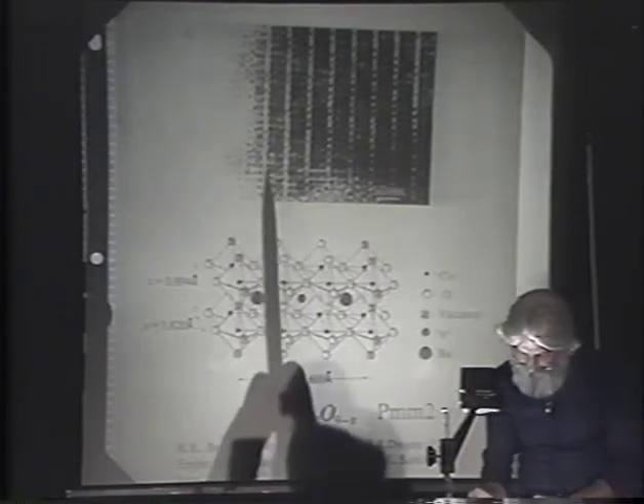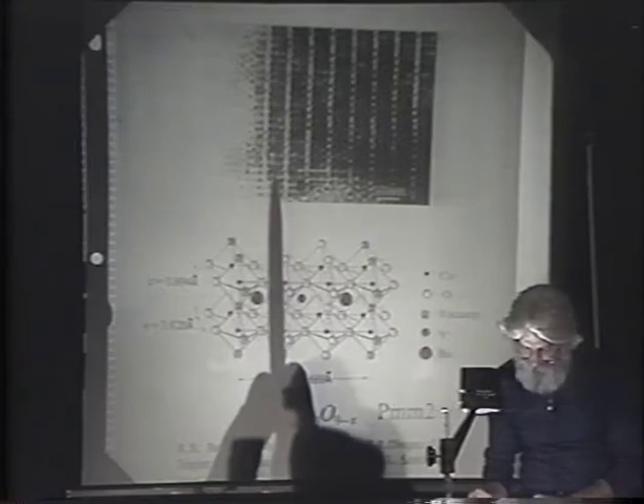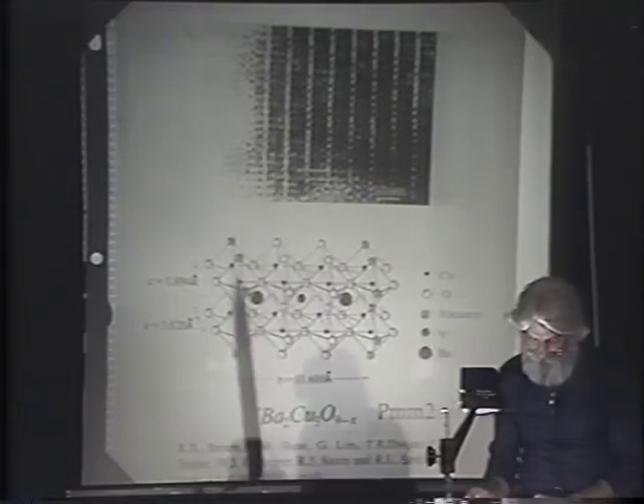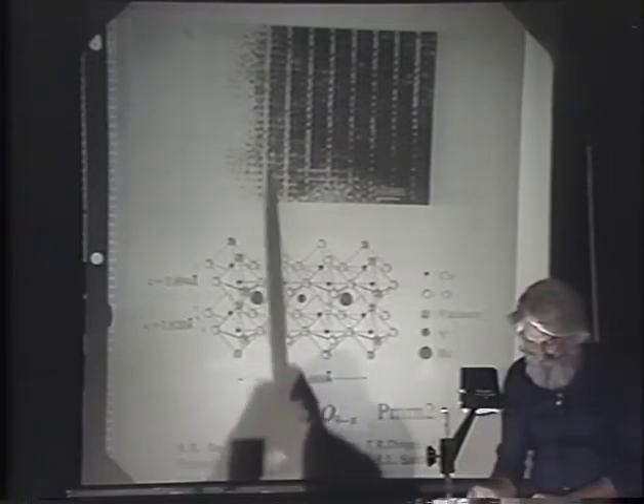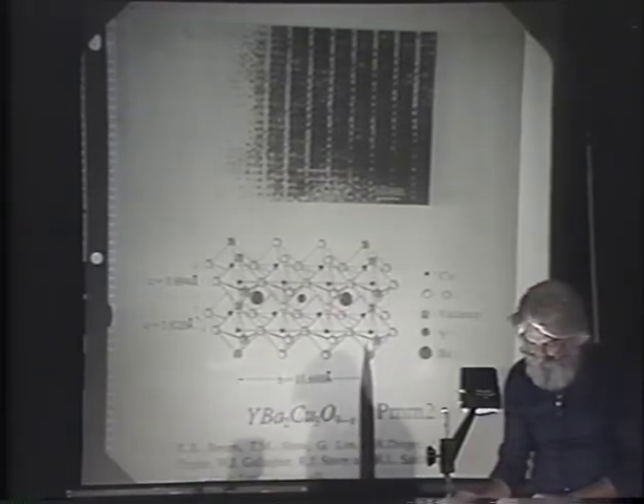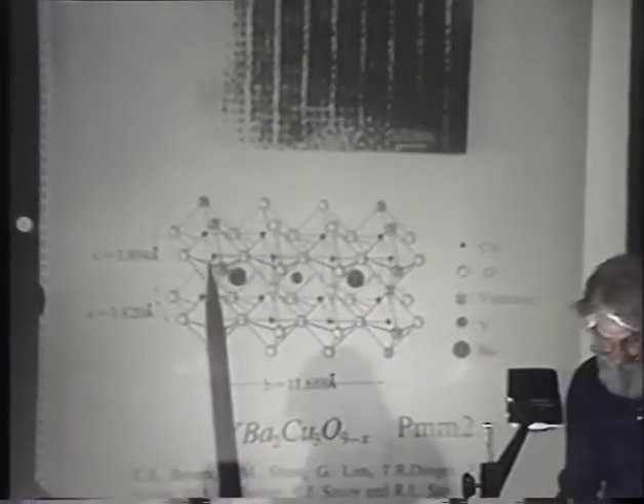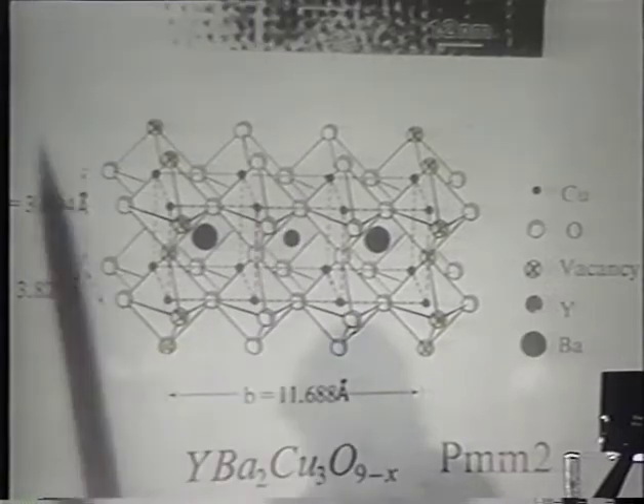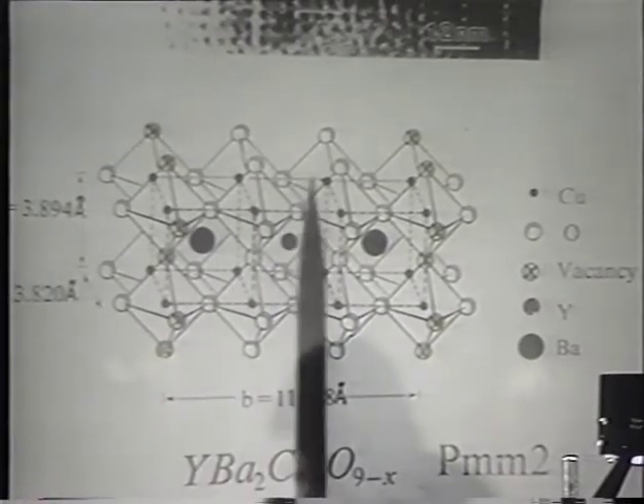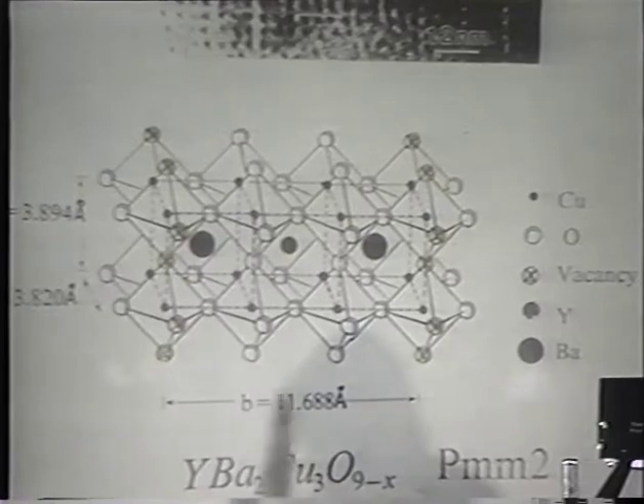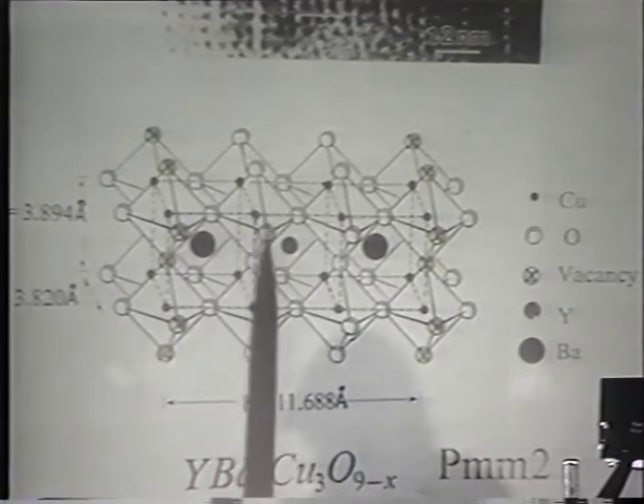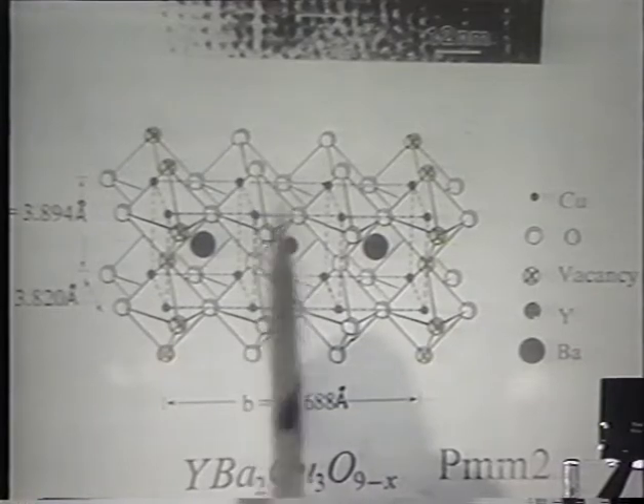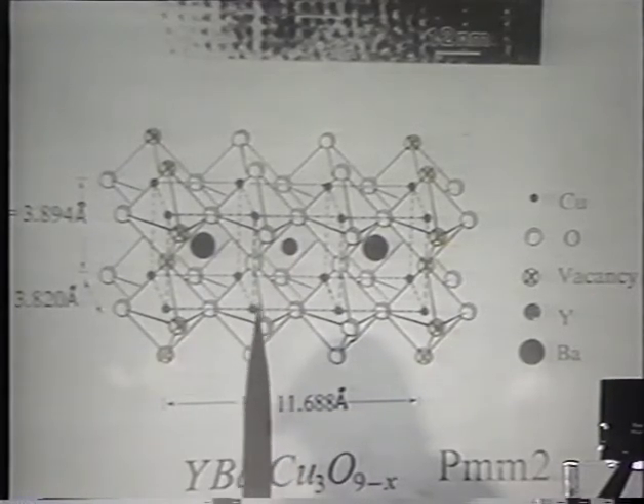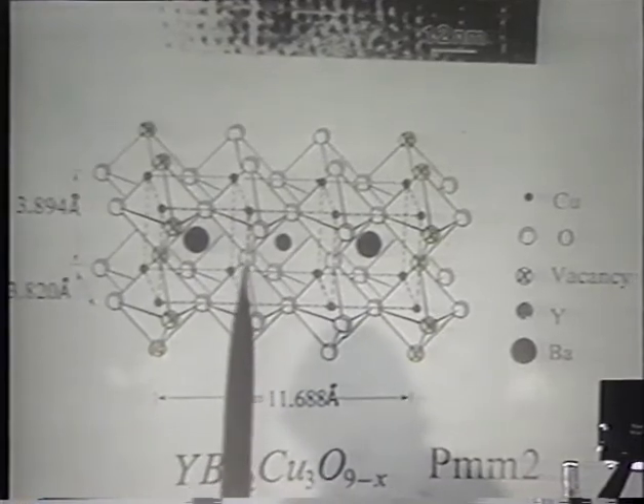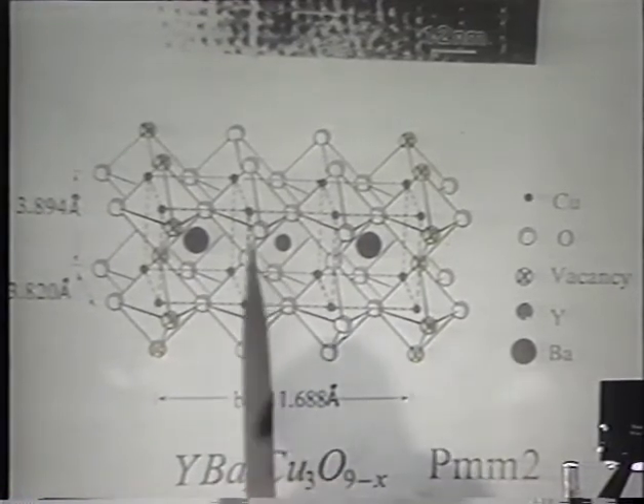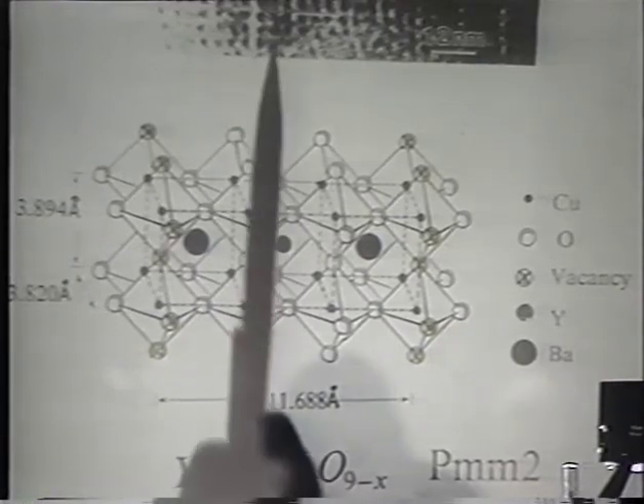The other thing to notice on this micrograph is this large white space in here. Our beginning thoughts were that these were oxygen vacancies in the copper basal plane, and you see here we've marked possible candidates. We really can't say anything about the oxygen vacancies in the yttrium plane. They could or could not be there according to these data. If they are there, I'm still a little concerned about how yttrium 3+ would collect enough negative charge to satisfy its valence. Perhaps it's not yttrium 3+, perhaps it's some other valence, and that should spur on some core level spectroscopy on yttrium. Okay.